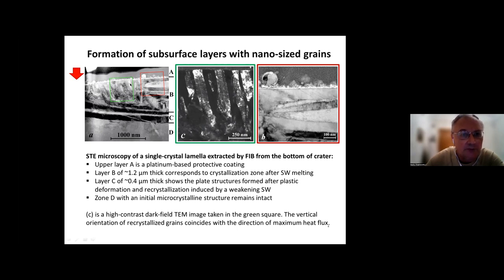In order to see more detail, a high contrast dark field image was taken from this green square, and you see vertically elongated crystalline grains, whose directions almost coincide with the direction of maximum heat flux, because on the top we have high temperature and in the depth low temperature. The heat flux is oriented vertically. The red square demonstrates some very strange, unusual behavior with a different orientation of the newly formed crystalline plate. Actually, we have not analyzed what happened here because it's just an exception. Most of the material consists of vertically oriented grains, so we just skip discussion of this red square.